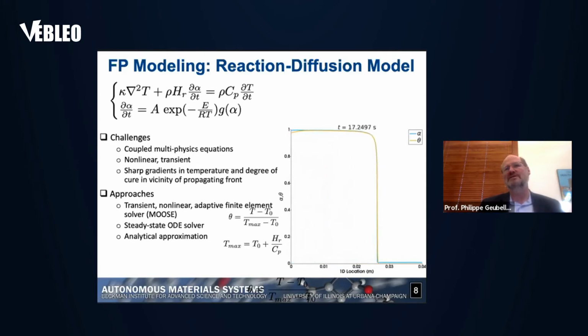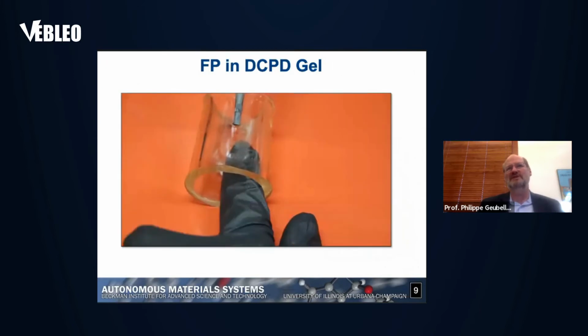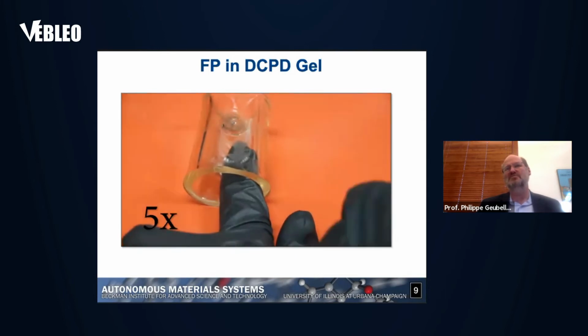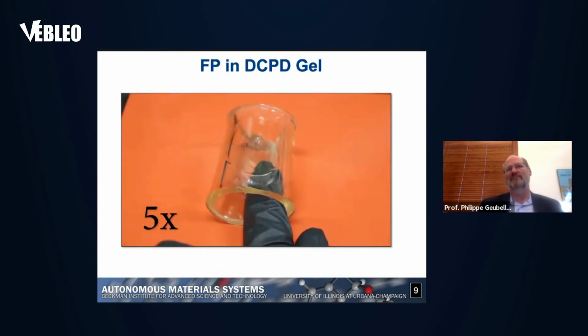What you have here is an example of a transient simulation where you can see the front propagates from left to right. There is some transient, but after a while, the front starts to propagate in a fairly stable fashion. You can see a very sharp front for both the temperature, which is the yellow curve, and the degree of cure, which is the blue curve. The front propagates through the entire domain, just like in the experiment. Before validating this model, I want to also emphasize that frontal polymerization takes place also in a gel. So this is a partially cured polymer, right?